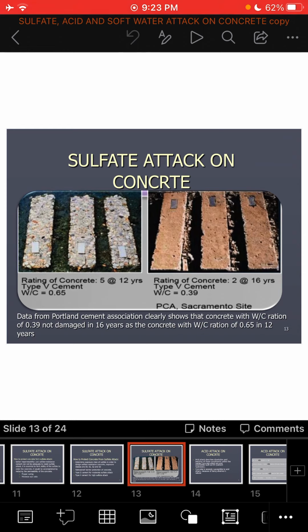Those beams with lower water cement ratio tend to protect better against sulfate attack than those with higher water cement ratio. Data from Portland Cement Association clearly shows that concrete with water cement ratio of 0.39 was not damaged in 16 years, while the concrete with water cement ratio of 0.65 was damaged in 12 years. It shows that better impermeability is the best way in order to protect concrete from sulfate attack.